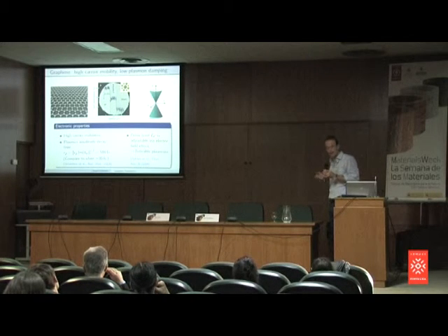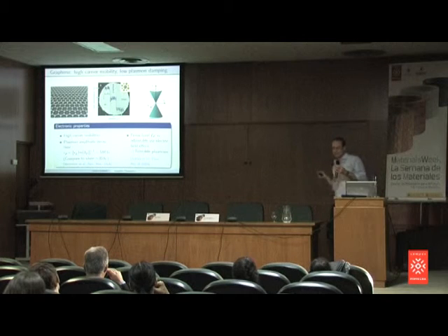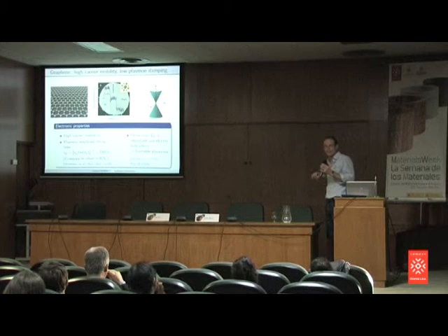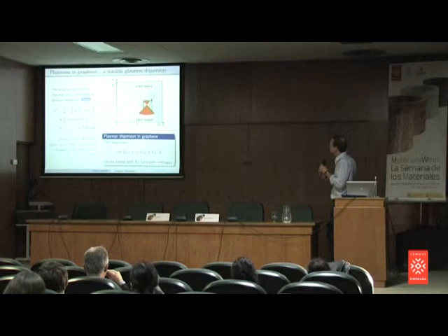And the other thing has to do with the very obvious fact that graphene is just atomically thin. What happens if you have a sheet of graphene, let's say, and apply an electrostatic field, a gate voltage? You can shift the Fermi energy, no? You can shift more or less the filling where the electrons sit in this dispersion here, from here to there. And very nice. But it turns out that this also gives you tunable plasmons. You can turn a knob in the laboratory and tune a plasmon dispersion. Goes like this, no?